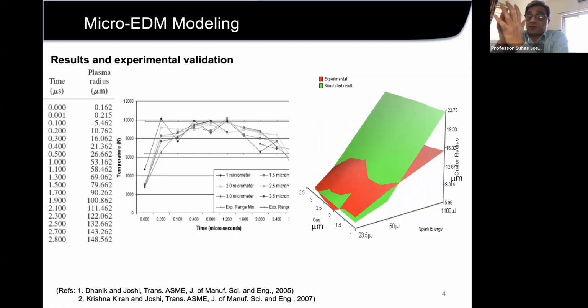And that was because we have not considered resolidification of the evaporated material. So when the spark forms and a cavity is formed in EDM, after a while, there is a certain amount of resolidification of the metallic layers, and the actual dimension of the crater formed is smaller than what it initially is. So that's where the larger energies are used, and the differences are much larger at that point.